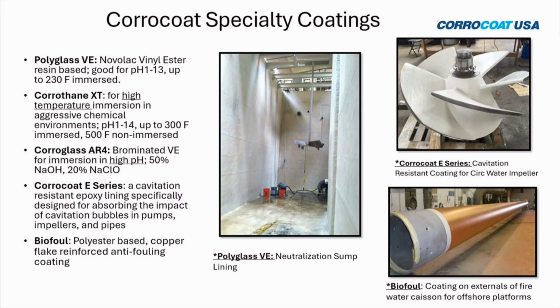Corrothane XT is a high temperature version of the VEF. It's a vinyl ester urethane copolymer. That'll get up to 150 C immersed and 500 F, that's 260 C non-immersed. We have the AR4. So the Novolac vinyl ester is really good. It uses cobalt as a promoter. The problem with cobalt is in high pH situations, the cobalt can be attacked. So we will substitute the brominated vinyl ester, the Corglass AR4, in those situations.